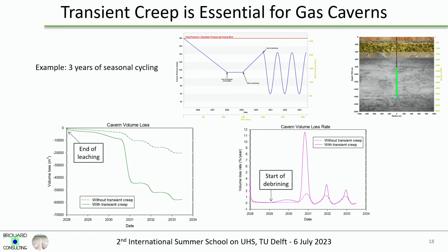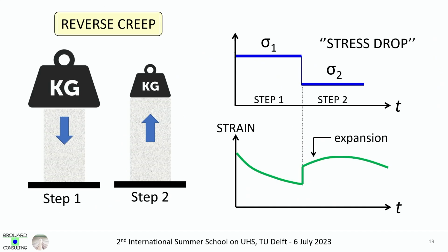Important, this slide. I've seen a few recent reports made in Europe that make some calculations with hydrogen caverns, fast cycling, and so on, but without considering transient creep. There was only steady state creep and pressure solution creep. So only steady state, no transient mechanism in this. And I just made a very simple calculation of a hydrogen cavern with a 3 seasonal cycle like this, comparing with and without transient creep. And as you can see, on the bottom left, you have the loss of volume of the cavern. Bottom right, this is the volume loss rate. You see there's a big difference. So it means that you have to include a transient mechanism in your creep law, and it's not always very obvious because the implementation in the finite element code could be quite complicated.